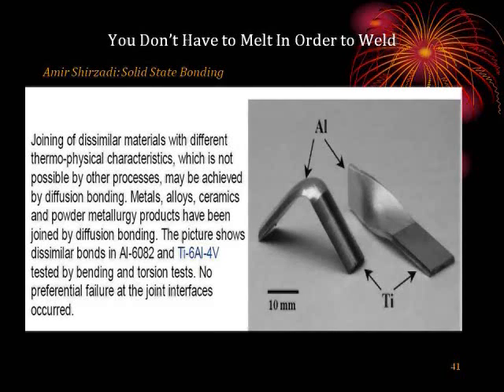This is a picture of a piece of aluminum welded to a piece of titanium. The difference of their melting points is something like 1100 degrees C. And yet, by using solid state welding techniques, you can weld them together very well.